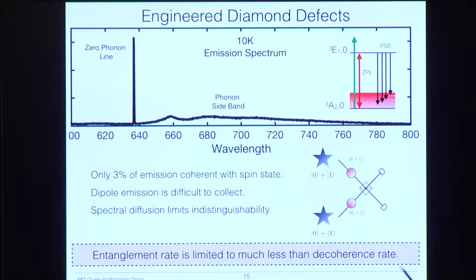The second problem is that the NV is a dipole, and dipole emission is notoriously difficult to collect into a single optical mode that can be used for transport, such as a waveguide mode or a fiber mode. And the third thing is that we have something called spectral diffusion. Spectral diffusion is when there are moving electric fields nearby, which shift the levels of the NV center, changing the frequency of this transition ever so slightly. So because of that, currently the entanglement rate is limited to much less than the decoherence rate. We can, maybe if we try, do 1 every second or 10 seconds, that's like the fastest that anybody in the world can do it, but that's not fast enough for creating multiple entanglement events within the coherence of the qubit.